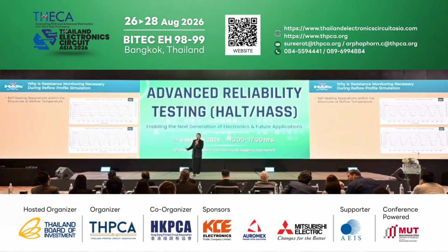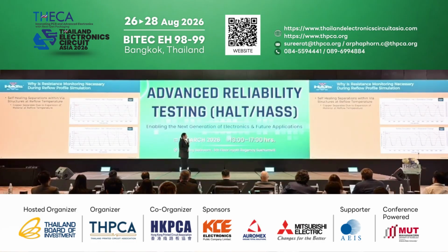It's an indication that this batch of coupons already shows a very early failure. And the graph on the bottom of the slide shows the coupons are already seeing opens. It's not just a high percentage resistance change.